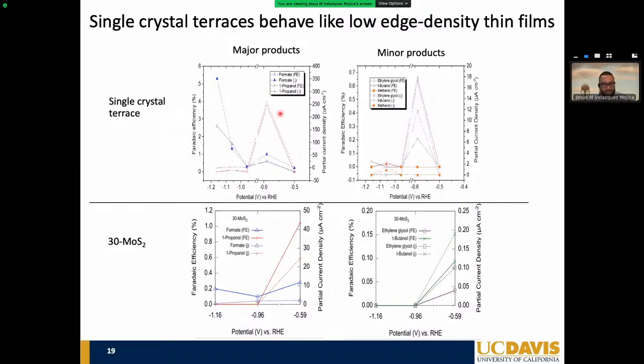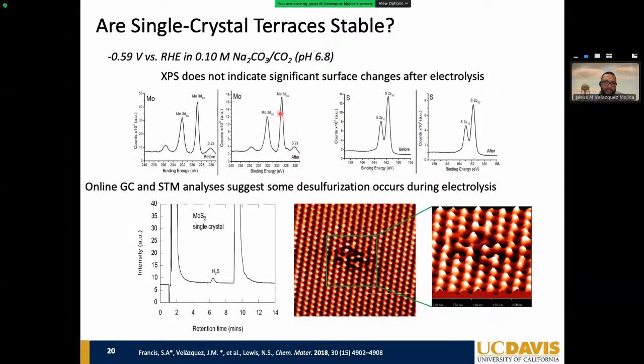So that made us excited that indeed, if we can control this synthesis, if we can control how we are exposing these surface motifs to the electrochemical environment, we will most likely have a surface that allows us to do carbon-carbon coupling reactions, which is rare in our field. But as you can imagine, there's more to it. So we covered our bases and did X-ray photoelectron spectroscopy to validate and make sure that we're not perhaps losing sulfur or that some weird decomposition is not occurring. When you compare high resolution scans of molybdenum versus high resolution scans of sulfur, you don't see much difference.